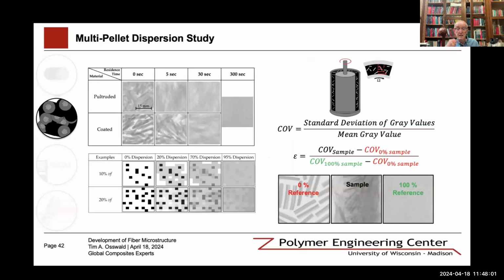So the next thing my graduate student Hector Perez did was finding a coefficient of variation in the different X-ray or micro CT X-ray devices. So, for example, he shows the pultruded one on the upper left-hand side, at 0 seconds you can still see all the fiber bundles there. At 5 seconds they're very well more dispersed. At 30 seconds even more dispersed, and then finally eventually you have one that is very well dispersed.